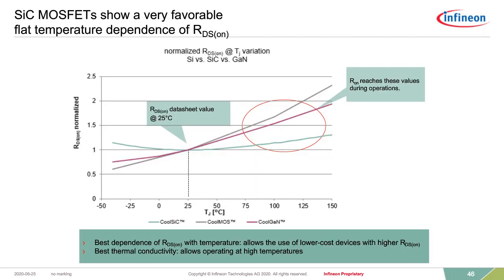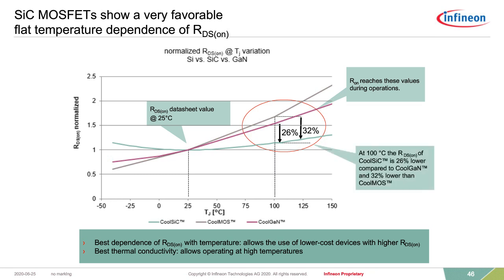Moving forward into silicon carbide, as mentioned, one of the key topics is the low temperature dependence of the on-state resistance, making the device a very good candidate for operating, for example, at 100 degrees junction temperature and higher. In this case, the effective R_DS(on) is significantly lower than that of competing superjunction and gallium nitride devices, which makes the device a prime candidate to optimize both for full load and partial load. So basically, it allows you to use a higher R_DS(on) than you would typically choose in a superjunction device.